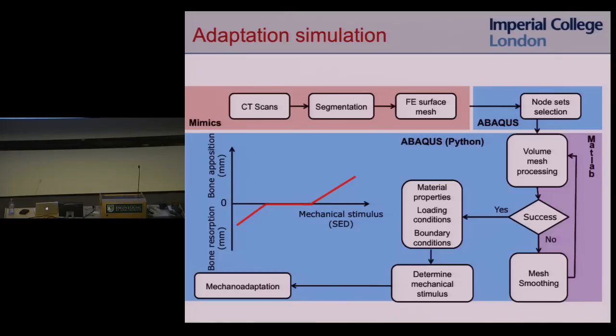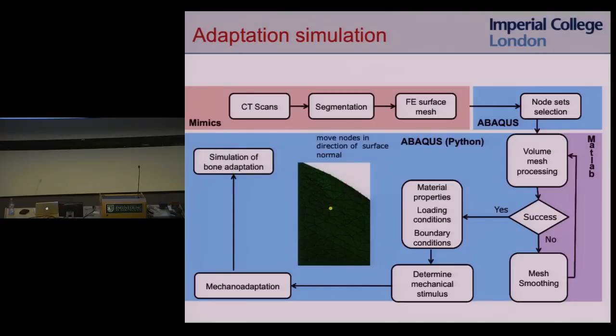So that's Wolff's law that I talked about at the beginning. If you load bone, you get more bone. If you don't load bone, it goes away. So that's represented in this mechanoadaptation rule. You then simulate bone growth. It's projecting really dark, but this is a surface mesh of the bone. Say we had very high stimulus at this point, what we would do is actually grow that in the direction of the surface normal. So that point would move. The point in that mesh would move in order to represent that adaptation. So we're growing the nodes on the surface, so it's periosteal adaptation. Periosteal means on the surface of the bone, and that's where we get the adaptation in this model.